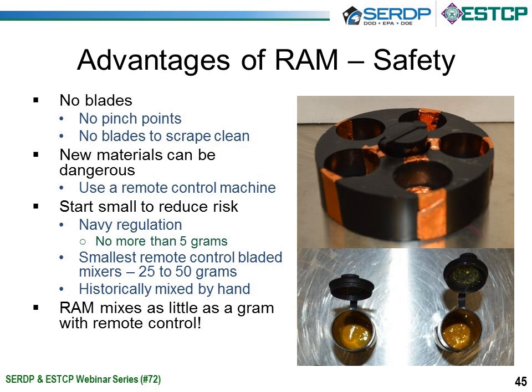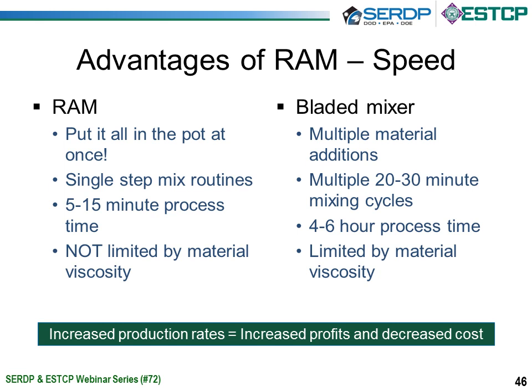On the bottom, you see a couple of containers that we have mixed material in, open. You can see finished propellant material there. Those are mixed at 5 grams, and so we can mix as little as a gram of material with remote control, which is a major advantage, because now we can get away from making hand mixes, which put the operators at risk. If we move on to slide 46, another advantage of the RAM is that it's very, very fast.